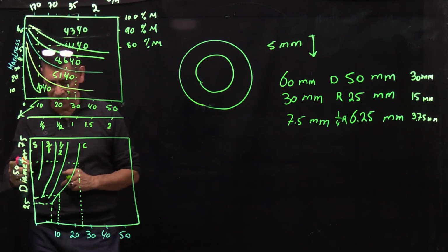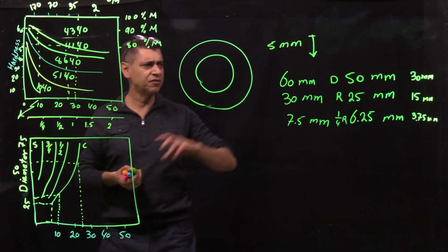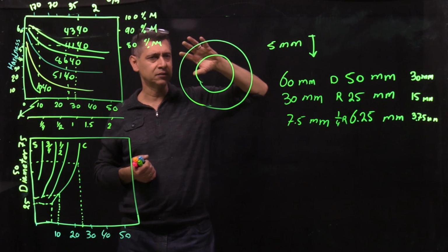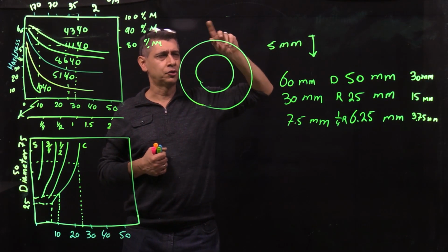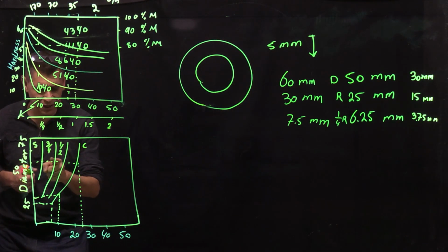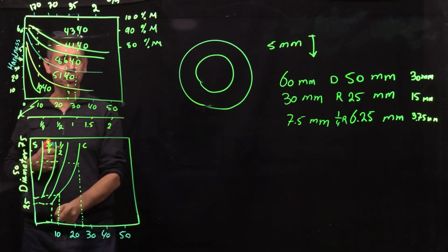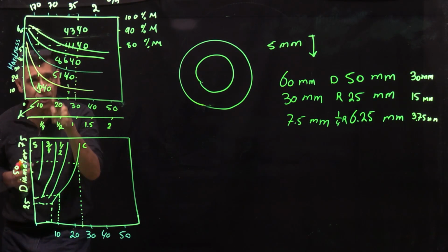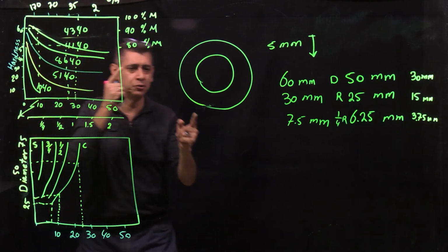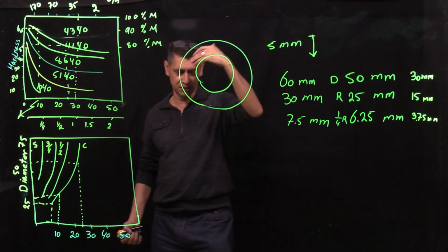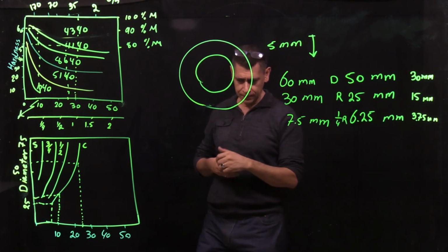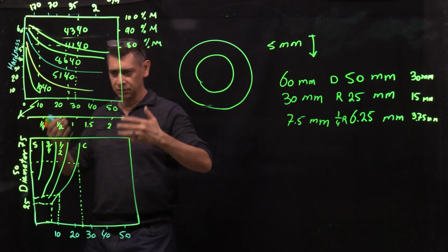Based on the diameter, you realize where that 5, or any number you have, stands. If it's near 3/4, you go find the 3/4 here. Then you find the cooling rate for the 3/4, and go back based on the alloy, find the hardness and check if it satisfies the design criteria or not. You have to do it in exactly the same order.